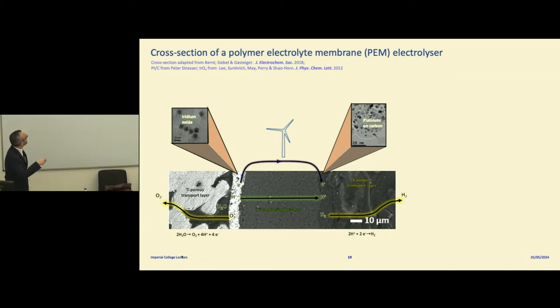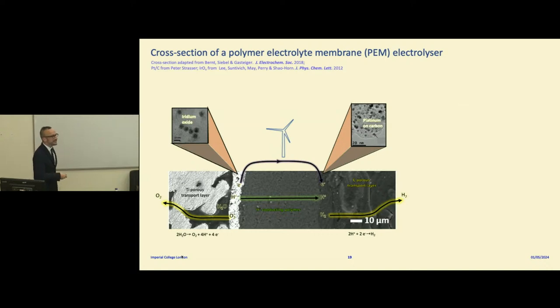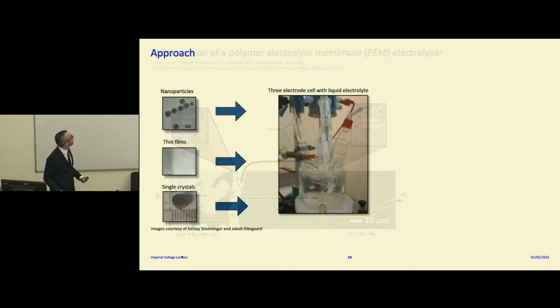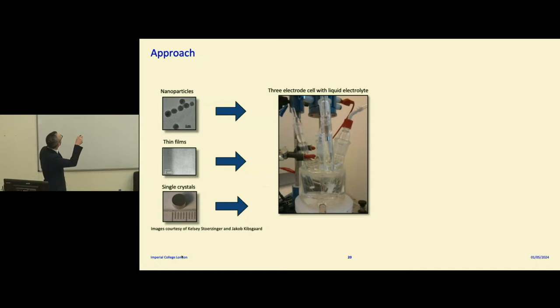But you can imagine doing it is not that easy because there are a lot of different steps to put it together. So it's difficult to see what the fundamental effect of changing the material is. Even if you look at these materials, you can see these platinum nanoparticles, these black dots, have a lot of different sizes and shapes, and each different size will have a different reactivity. So often what we do is look at more model systems and model conditions where we're changing parameters more carefully. For example, we often look at size-selected nanoparticles.